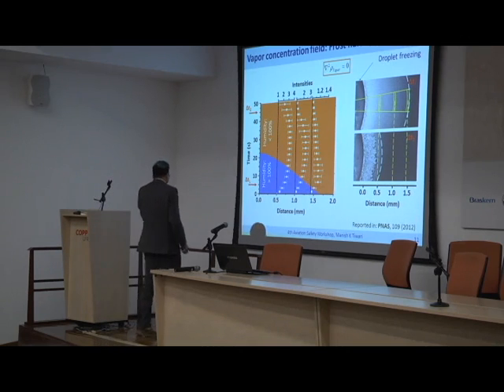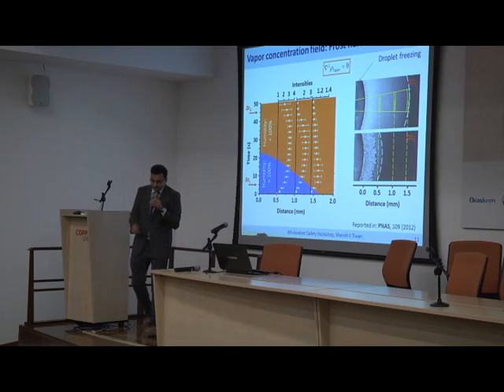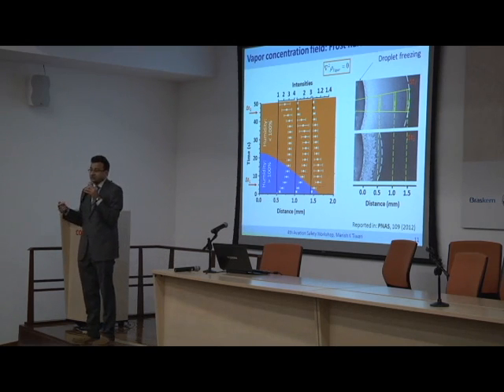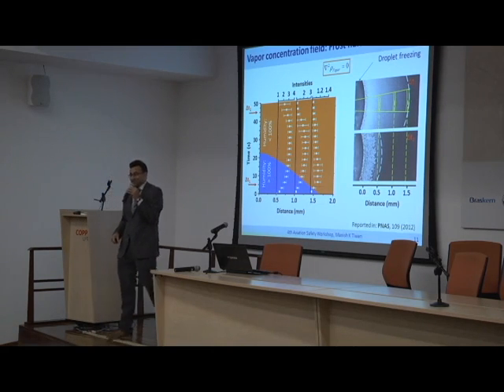And if we do that, what you see is at any location corresponding to this simple diffusion model-based prediction, I've got growth of my condensate drop, and then right about at this peak, it matures and then starts to come down and evaporate. What's the message of this? Other than the fact that this is a very complicated figure, I would like to emphasize the fact that freezing is not a single phase change problem. It's not just about water changing into ice. Depending on the humidity conditions you have, you may have evaporation, condensation, etc. going on at the same time. Life is a little more complicated than we think.